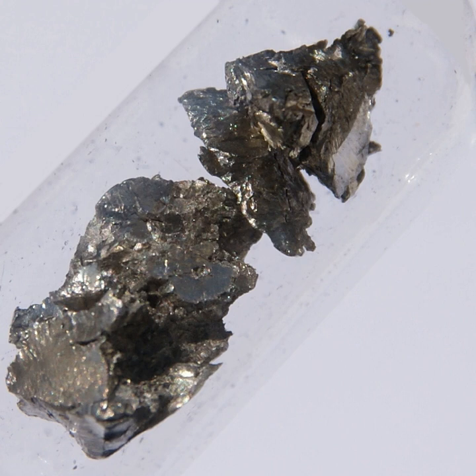The dark-colored praseodymium(IV) oxide, PrO2, is the most oxidized product of the combustion of praseodymium and is only obtained by reaction of praseodymium metal with pure oxygen at 400 degrees Celsius and 282 bars. The reactivity of praseodymium conforms to periodic trends, as it is one of the first and thus one of the largest lanthanides. At 1000 degrees Celsius, many praseodymium oxides with composition PrO2-x exist as disordered, non-stoichiometric phases, but